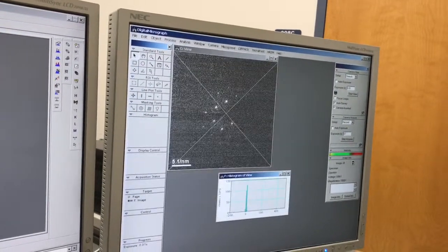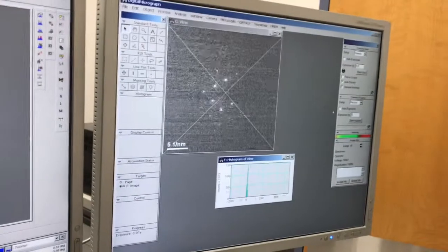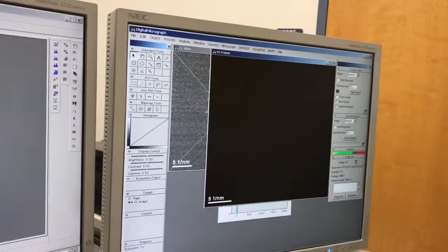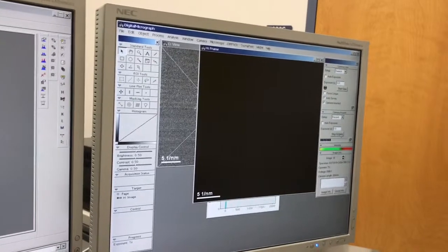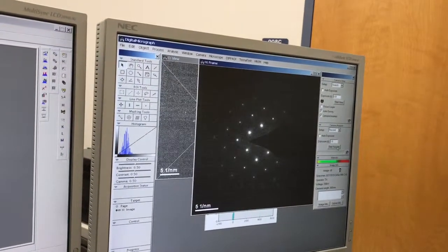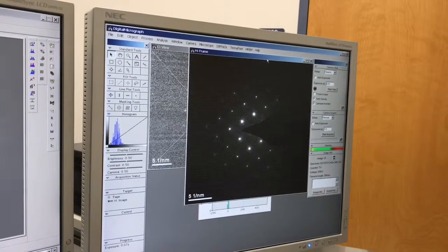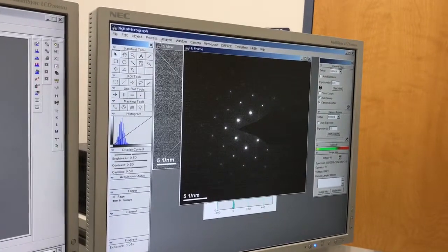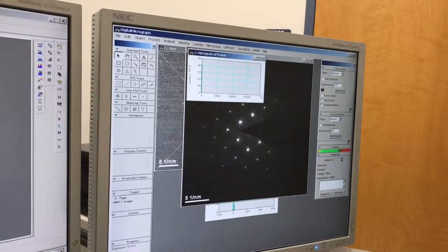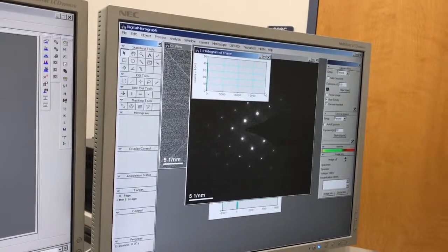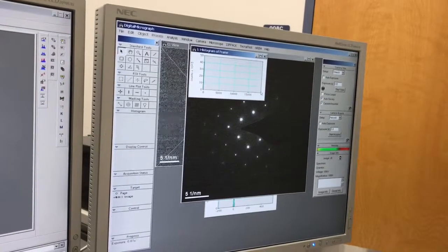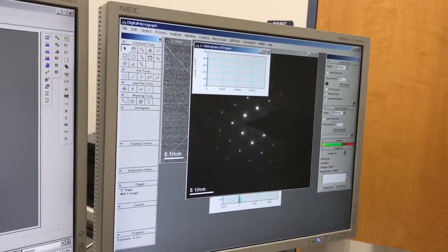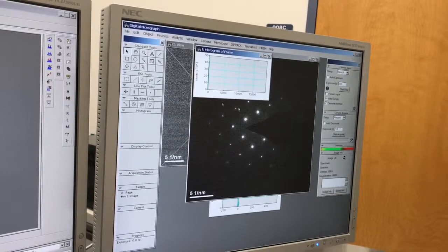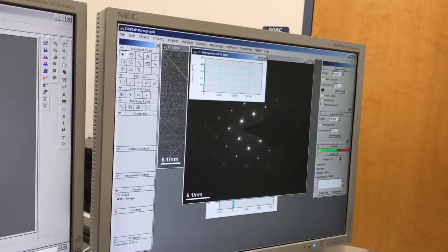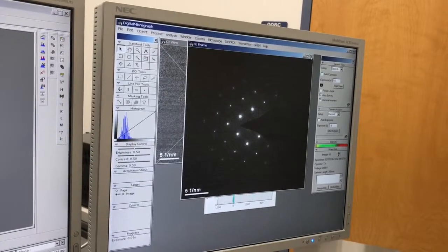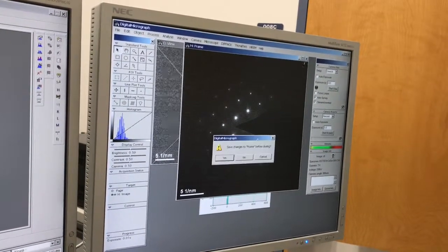So I'm going to close this, change this to 1, and we'll do an acquire. Again, more is better in terms of signal to noise, but you have to be careful that you're not exceeding the dynamic range. This obviously looks a lot better. If I do analysis histogram, my max counts is now around 20,000, which is still under half of the dynamic range. So realistically, I could go to 2 seconds here, and I should get to a max of around 40,000, which should still be safe, because the cutoff point on here is about 65,000.